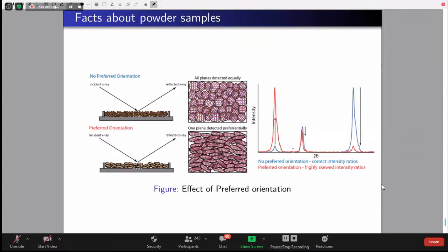But what I mentioned was for the Scherrer formula. Scherrer is going to take very gross approximations. The best one is to take the lower angle peak, which is around between 20 and 30. If you have a peak there, you can take that, where your instrumental broadening is going to be very, very small. Then strain is for that family of planes alone, no? That peak alone, yes, ma'am. Okay, sir. And crystallite size is also for that family alone. Exactly, ma'am. That we can't attribute to the entire sample.